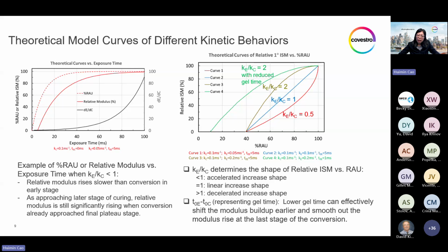Before we show our actual new coating kinetic behavior, it is interesting to see theoretically how it looks when this ratio equals 1 or is higher than 1. When it equals 1, the modulus increases linearly with conversion. When it is higher than 1, it starts to show a decelerated increase in shape, which means the rise of modulus versus conversion slows down at the last stage of the curve. And if coupled with a reduction of induction time, this green curve shows that even with the same ratio, when the induction time is reduced, the curve is further smoothed out into a near flat plateau at the last 20% of conversion, which is where commercial coating cure degrees typically are.